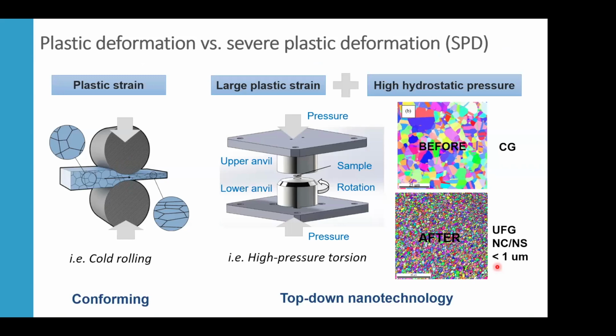So just as a brief introduction, I would like to talk about why we do high pressure research, especially high pressure torsion, in metallurgy, and apply it to a wide variety of metal alloys. So traditionally, when we talk about traditional forming methods like cold rolling, as you see on the left, the deformation is carried out at ambient pressure. So that's when we introduce a lot of strain, defects and dislocations accumulate, and grains orient themselves according to the most favorable slip along the deformation direction, and that will cause grain refinement.